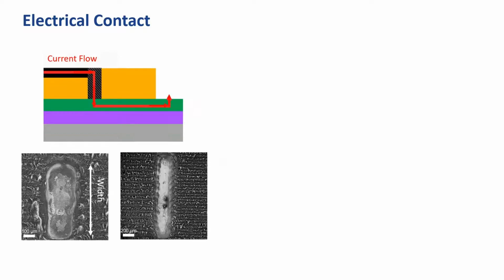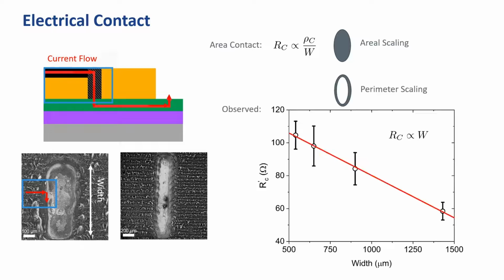The geometry of the contact isn't obvious. We know from the continuity between the top surface and the base metal they must connect, and that having more contact plugs decreases the resistance, but it isn't clear how to best scale this contact method. By varying the contact width, the dimension perpendicular to the direction of conduction, we can gain some insight. If it is a classical area contact, we would expect the resistance to decrease as 1 over the width. However, when we construct a series of different contact widths and calculate their contact resistances, they instead decrease linearly with the contact width, indicating perimeter scaling instead. Therefore, in using this method of contact, numerous small contacts should be preferred to fewer large contacts.